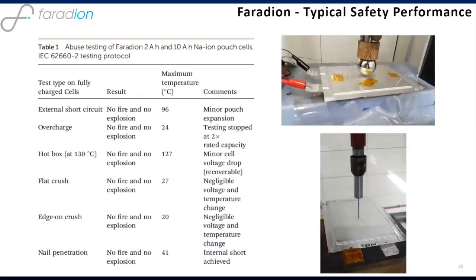A big advantage for us, and we claimed this when we started this work, was because of the intrinsic safety of the sodium ion chemistry, we should get better safety abuse characteristics. And we've done huge numbers of tests on all kinds of sizes of cell, and also using different testing protocols for the safety. We're showing IEC testing here, but we've also done UL and UN DOT, and we've never had any incident. Shown on the right-hand side are a crush test on the top and nail penetration on the bottom. We've had no problems with any of the tests, including the crush, hot box and nail penetration.